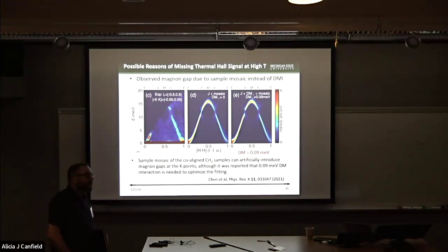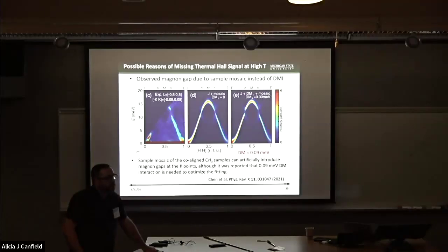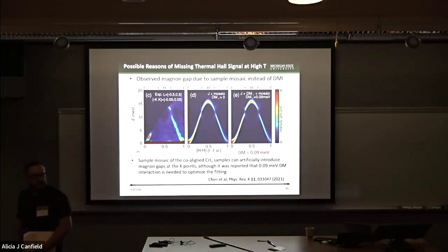Yeah, I also had a comment that, especially for layered materials, changing the geometry so you measure a thermal current in the C direction is a very good way of deconvolving the phonon contribution from others, because basically only the phonons propagate in that direction. Yeah, this is a very good point, but unfortunately, in reality, it's extremely challenging to apply the thermal gradient in the C direction. The thickness of the samples that we measure or that we grow is in the order of several tens of micrometers thick. So it's almost mission impossible for such a measurement.